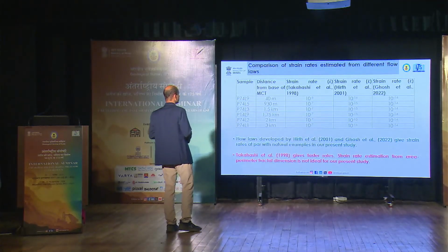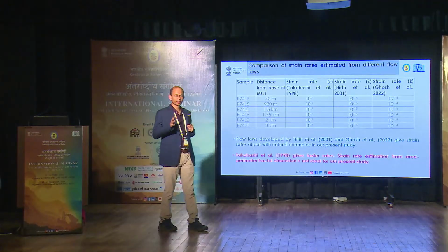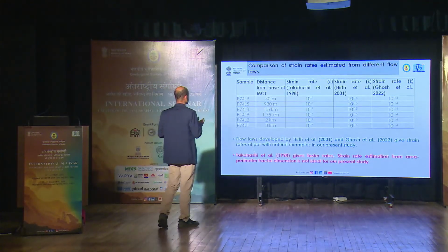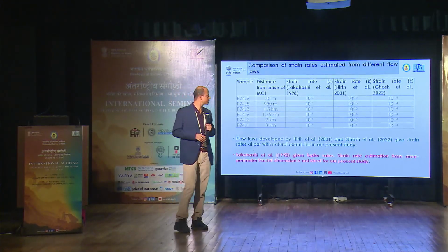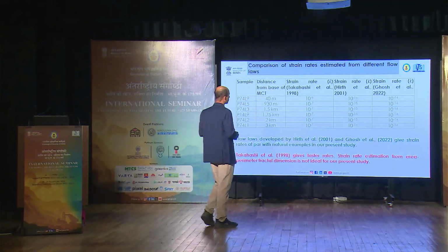Next. So when we compare the strain rates estimated from different flow laws, what we find is that the strain rate based on the area perimeter fractal dimension is giving 10 to the power minus 8 to 10 to the power minus 7, whereas those using the flow laws using the differential stress give us 10 to the power minus 16 to 10 to the power minus 14.